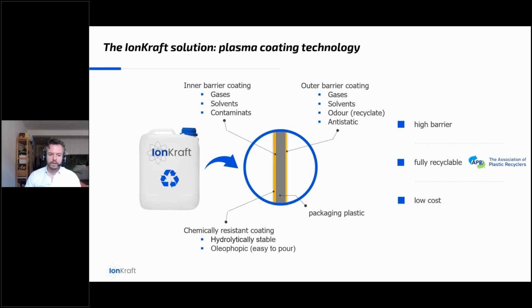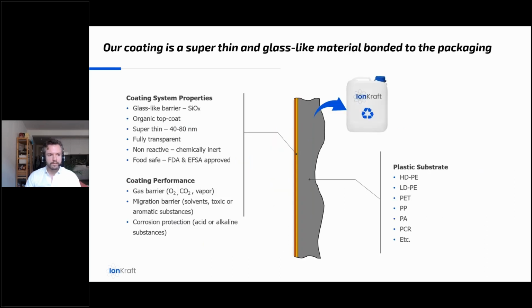So what does the coating look like? So basically, what we have is a silicon oxide barrier coating, which provides the barrier. We have an organic top coat. That is the coating that we developed, especially in the last 3 years. The coatings are super thin, so we're talking about coating thicknesses which are below 100 nanometers. They are fully transparent, chemically inert, and they're completely food safe already. So they're already approved by the FDA and the EFSA to be in contact with food applications.